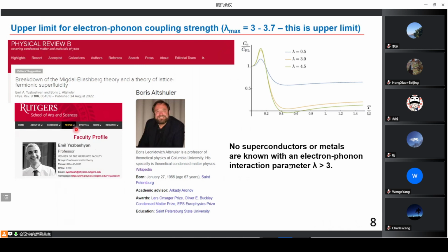This year, two guys, Emil Yuzbashyan and Altshuler, published a very important paper in Physical Review B, 2022. They found that there is a clear theoretical limit for electron-phonon interaction in any material described within Migdal-Eliashberg theory. They found that the superconducting state will not be stable if lambda is over 3.7. Here, I just would like to remind you that all previous experimental measurements for materials gave lambda less than 3. We do not know any conventional superconductor with an electron-phonon interaction coefficient higher than 3. And they found that actually 3 is close to the maximum possible. In fact, in their theory, they found that maybe in some cases we can reach 3.5, 3.7. So that's the absolute maximum possible lambda.